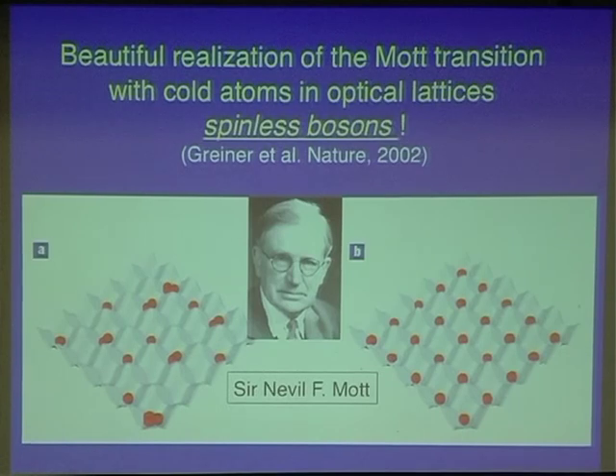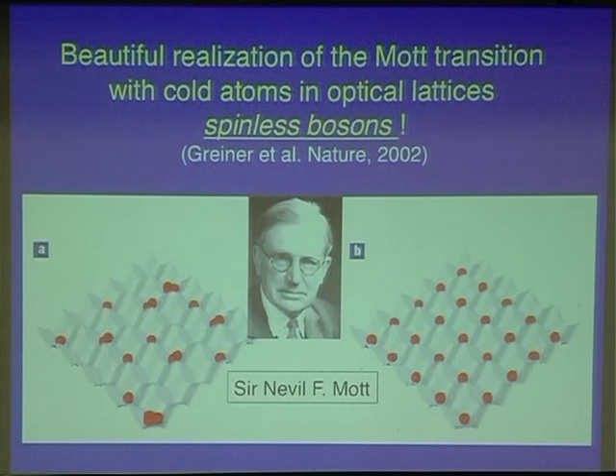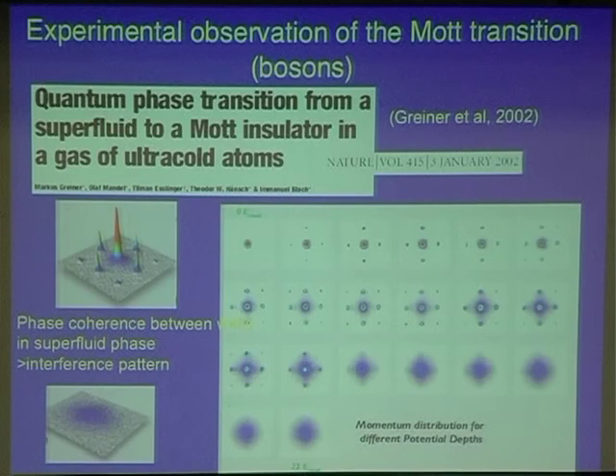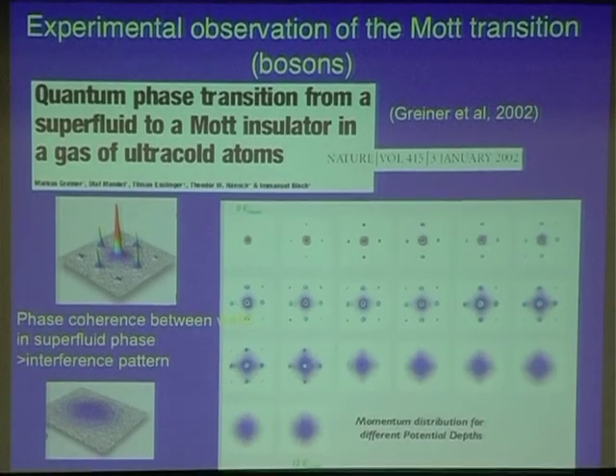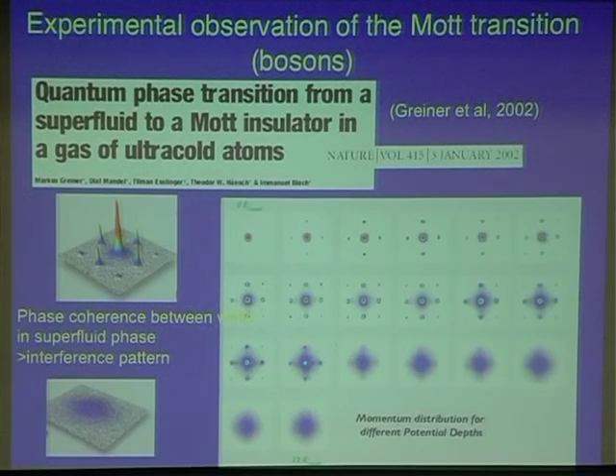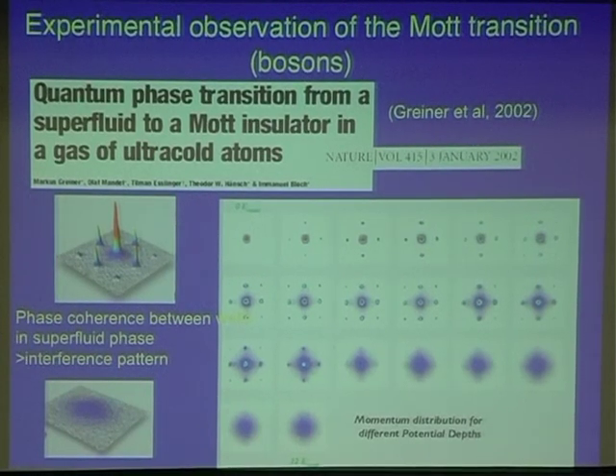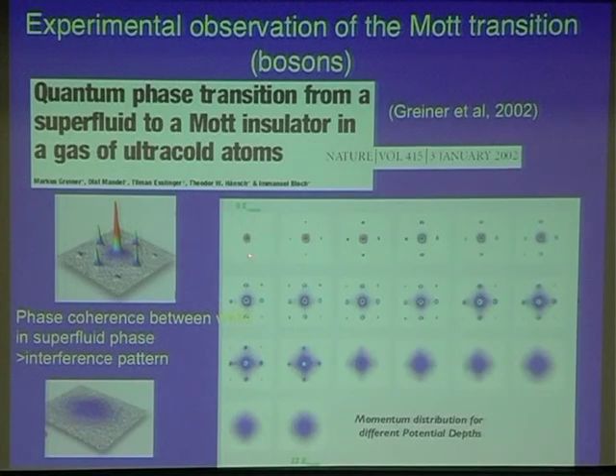One of the beautiful experimental demonstrations that was done about 10 years ago in this field is precisely to show that if we control these parameters, we can induce the phase transition between the superfluid state of bosons and a Mott insulating state of bosons. So Sir Neville Mott comes into quantum optics. This is the experiment. It was done by Markus Greiner, Tilman Esslinger, Immanuel Bloch at that time in Munich. And what you see here is the interference pattern resulting from all the individual condensates in the different wells of the lattice. As you crank up the depth of the periodic potential, you see here that there is a beautiful Bose-Einstein condensate, and here that it's completely gone. So you interpret this by having gone from a superfluid to a Mott insulator.